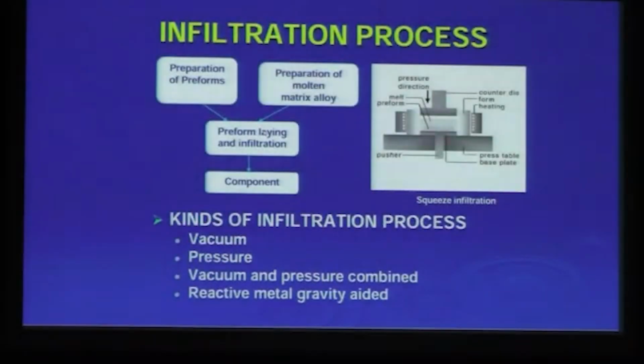Another process we are working on is the liquid metal infiltration process. Here what we do is we make a porous ceramic preform, and this ceramic preform is placed in a preheated die in a hydraulic press. The metal, aluminum alloy or the required alloy, is melted in a separate furnace, then poured into the die, and it is infiltrated through the porous region of this preform, and the composite is made. This particular process is used to make the thermal management plate for our light combat aircraft.